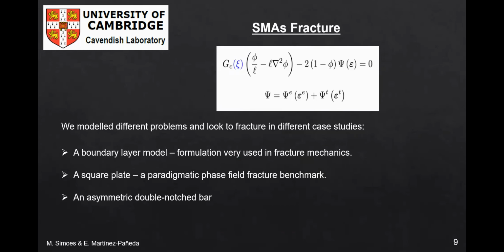And what we have done is to propose the first formulation of phase field fracture for shape memory alloys. And there are two key elements in our formulation. One is that the toughness of the material can be made dependent on the martensitic volume fraction. We know from experiments that the toughness of the martensite and the austenite phases can be quite different. So we believe that it is important to have this heterogeneous fracture energy. And we do so by using simple homogenization. The second element is the fact that the driving force for fracture is not just the elastic strain energy, but we also consider the contributions from the transformation strains. And we implement these numerically into finite elements.